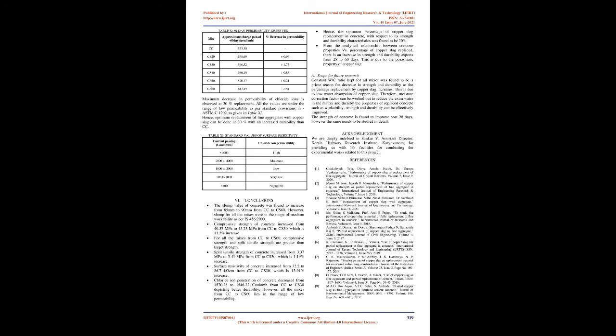6. Conclusions. The slump value of concrete was found to increase from 65 mm to 90 mm from CC to Cs60. However, slump for all the mixes was in the range of medium workability as per IS 456:2000.